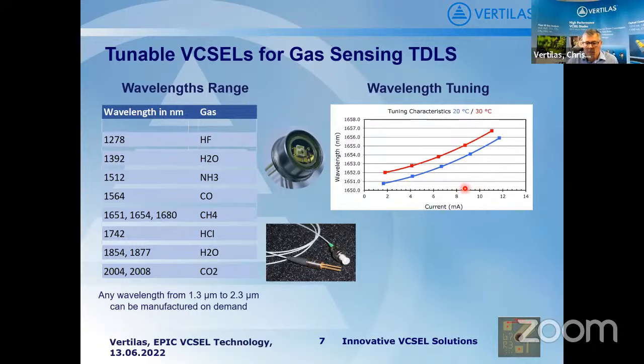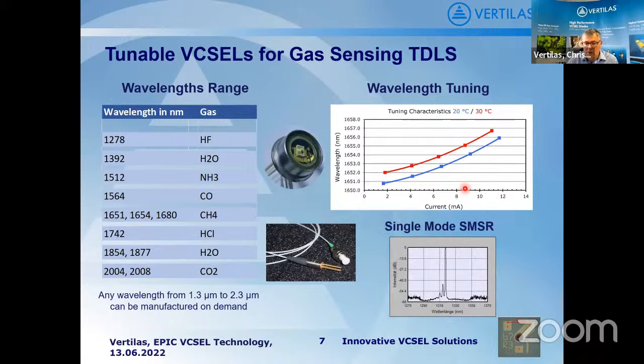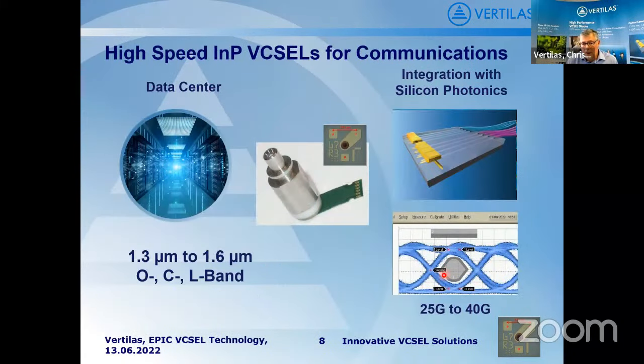What's very important, of course, is the tuning for this TDLS market. Our lasers can be tuned by around 4 nanometers by bias current. And what's also extremely important is, of course, the single mode performance. It has 40 dB or more of side mode suppression ratio, as well as a very narrow line width. Okay, looking at the next market, optical communications. We can produce products here for all kinds of bands, O-band, C-band, L-band. Our lasers can also be integrated with silicon photonics and show very high performance.